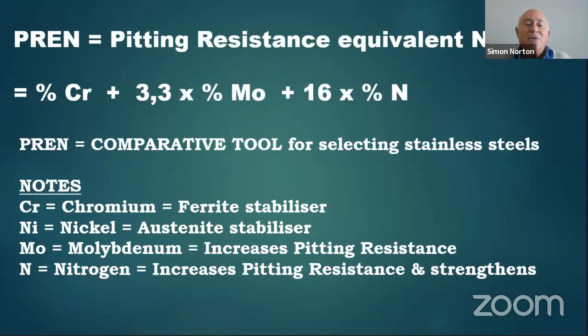And just as a matter of interest, chromium is known as a ferrite stabilizer, nickel as an austenite stabilizer. Molybdenum increases the pitting resistance, hence 316 stainless steel has molybdenum, and it has a better pitting and crevice corrosion resistance than 304, which has no molybdenum at all. And nitrogen has also been found to increase pitting resistance in stainless steel.